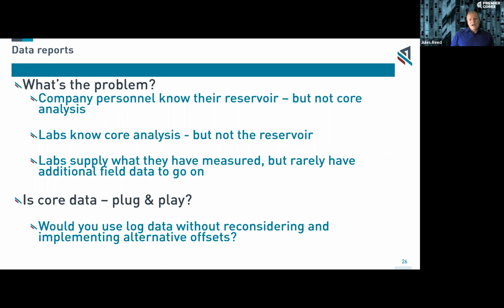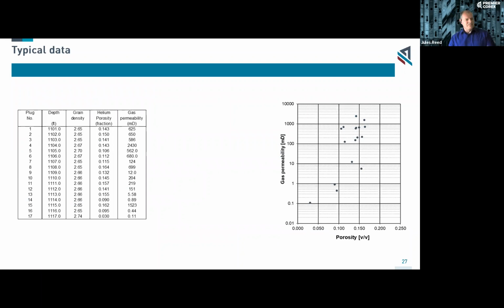You need to take the core data and consider those core data in the light of all your other data in that reservoir. So what are the data? Well, let's just take this one example. Here's a set of data, as you might get from a routine core analysis. You've got plug, depth, grain density, porosity, and permeability. On the right there, we have a plot from those data. We can see there's quite a spread of permeability for quite a small spread of porosity, around about 15% porosity spread, but over four orders of magnitude of change in permeability.